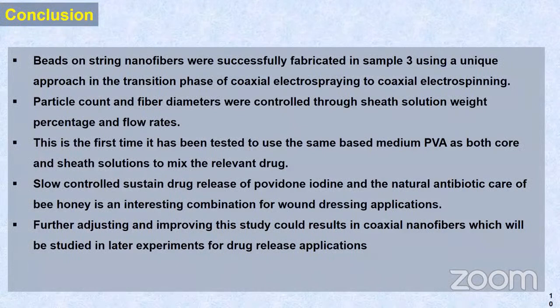As our conclusions, beads on string nanofibers were successfully fabricated in sample 3 using a unique approach in the transition phase of coaxial electrospraying to coaxial electrospinning. Particle count and fiber diameters were controlled through sheath solution weight percentage and flow rates. This is the first time it has been tested to use the same base medium, PVA, as both core and sheath solutions to mix the relevant drug. Slow controlled sustained drug release of povidone and the natural antibiotic nature of bee honey is an interesting combination for wound dressing applications. Further adjusting and improving this study could result in coaxial nanofibers, which will be studied in later experiments for drug release applications.